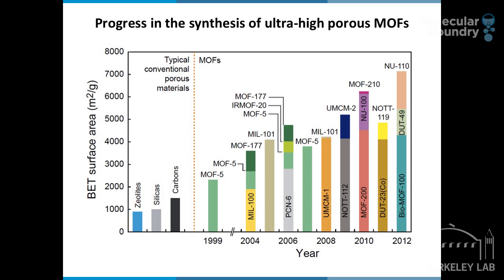Accordingly, after our initial publications, there was a lot of competition on who will achieve the highest surface area material. And so as you can see from this graph, MOFs in general exceed the traditional materials in surface area and porosity, and many more have been made. We have held and lost the record over the years, and the most recent record is held by our colleagues at Northwestern University, who reported NU 110, a material not very much unlike some of the structures that I have shown you, except with longer links.